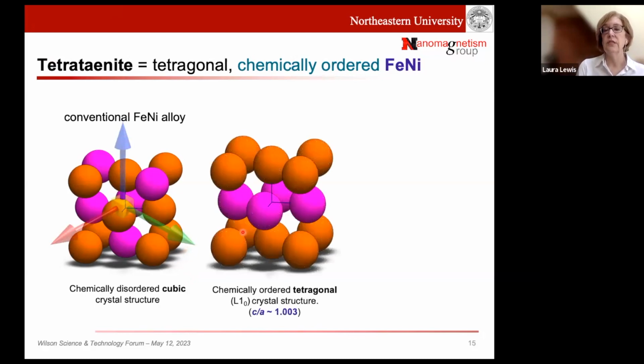This is tetrataenite. You can see that we have a slightly tetragonal structure. It's no longer cubic. We have extended this axis right here. And now this has this compelling chemical order or atomic order where if orange are nickel atoms, they align in a plane, then we have iron atoms and then nickel atoms, and they will continue to build on up to create something we call a superlattice. So those of us in material science understand a superlattice is a type of hierarchical order. And when these atoms align themselves, a very strong magnetocrystalline anisotropy, a strong moment, gets locked in, and it is now a useful one because it is uniaxial. It only goes up and down, and now this could be utilized for engineering purposes.